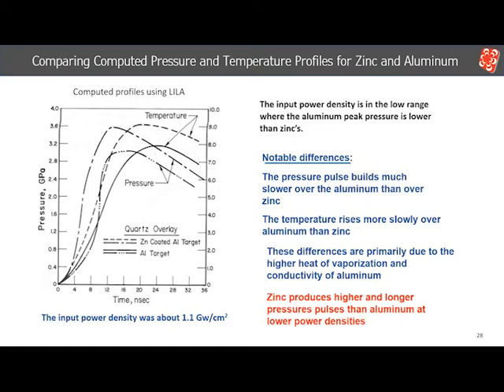There are two contributing factors. First, the surface temperature is lower for aluminum, which can be attributed to the loss of heat or energy from the vapor through the aluminum surface. Second, the delay in the pressure rise at the beginning of the pressure pulse for aluminum can be attributed to its higher heat of vaporization, consuming a significant amount of the beam energy early in the laser pulse. Because of these factors, zinc produces a higher and longer pressure pulse.